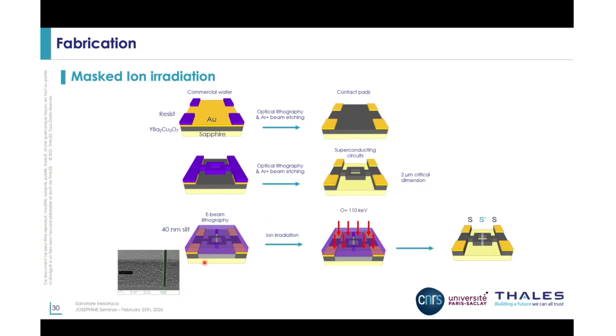First of all, because we now involve E-beam lithography, where we define slits, so openings into the resist of just 40 nanometers, which is going to be our mask that's going to be used for irradiation whenever we flood irradiate the sample with highly energetic oxygen ions up to 110 keV. And you see that actually we create the defects only in the local area, in the narrow area where the slit of the resist is actually open.